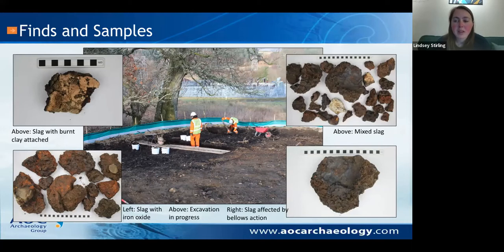One of the specific things the post-excavation team will be looking at is exactly how much iron is still within the slag. This will give us an indication of how effective the smelting process was at this site. Essentially, the less iron they find within the slag, the more efficient the process probably was. Many of the pieces of slag have rounded edges. We often call these hearth bases, where they form with a lovely rounded base at the bottom of the pit.